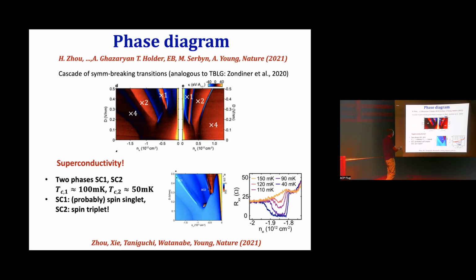But strikingly, you can actually study the spin state of the Cooper pair by applying a magnetic field. And from that, they deduced that the SC1 phase most probably is a spin singlet, like in a conventional superconductor, but SC2 is a spin triplet superconductor. Okay, so the 2 electrons in the Cooper pair actually form a spin 1, not a spin 0.